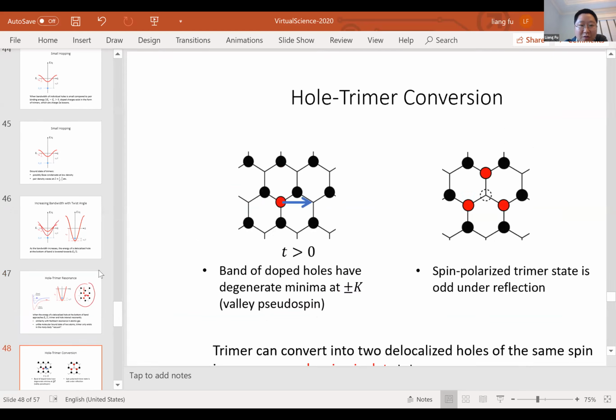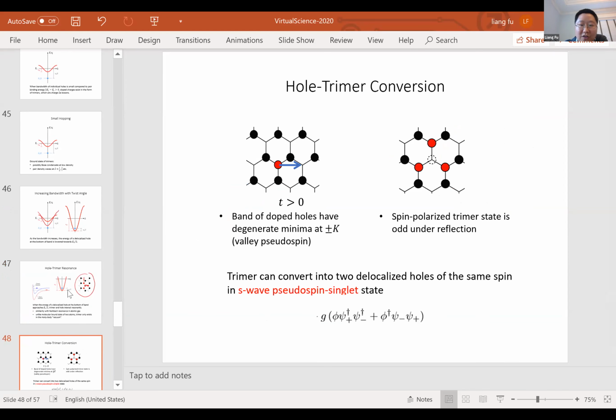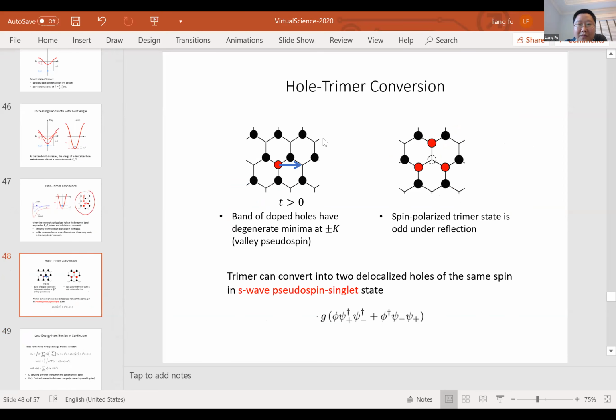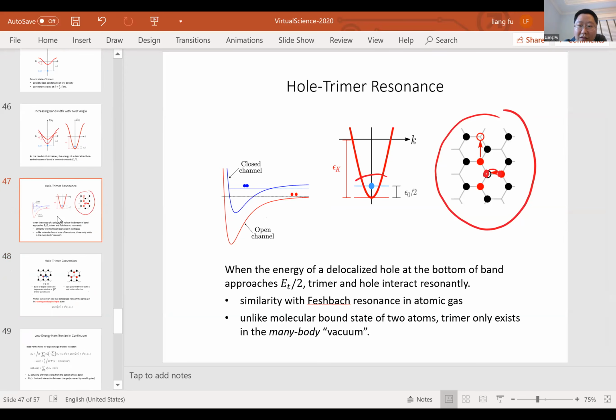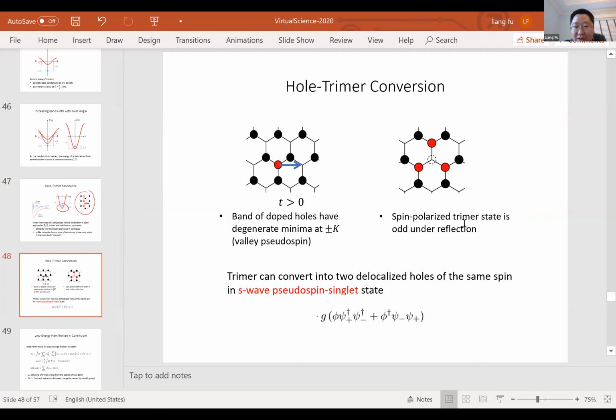So we can now go to the low energy limit. When we are in this regime, when the band bottom of the holes is close to the energy of the trimers, we can write down a low energy theory just involving the states near the band bottom. In this case, if we go back to the original problem, the neighboring hopping between the cation sites, the amplitude is positive.